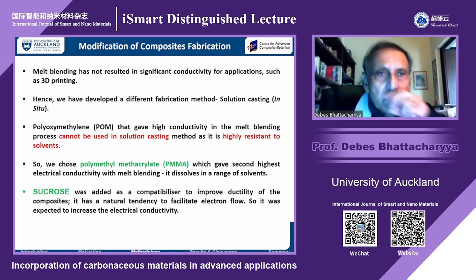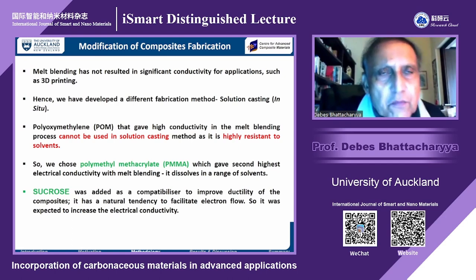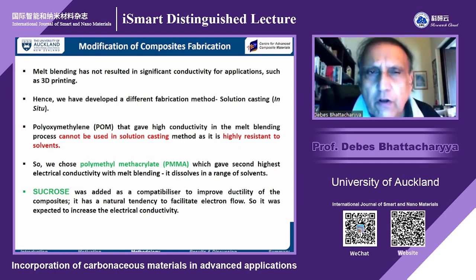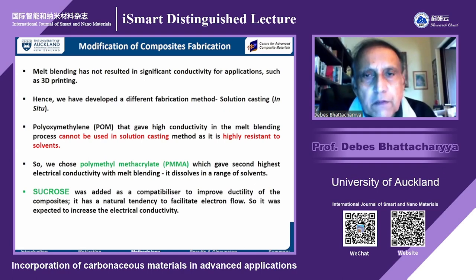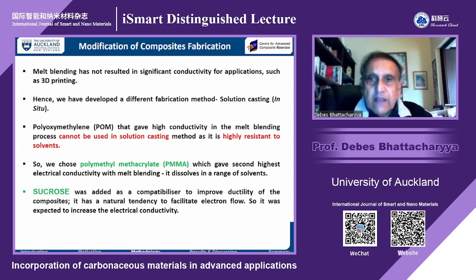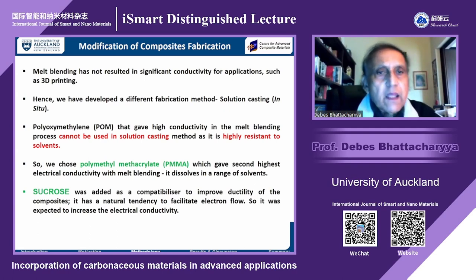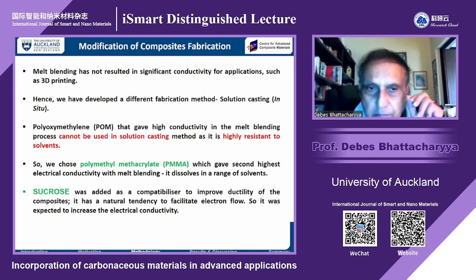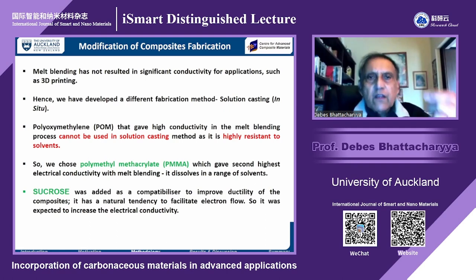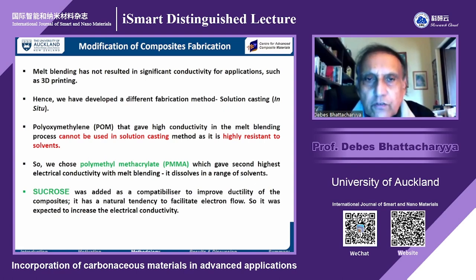Because our ultimate goal was 3D printing, and with that sort of conductivity, we were not prepared to venture into those things. So we thought solution casting in situ, only problem was that POM, which gave the highest conductivity in melt blending, cannot be used in solution casting method as it is highly resistant to solvent. So we had to compromise. Immediately, as soon as we started thinking of modifying the method, solution casting, we had to compromise. We could not use POM.